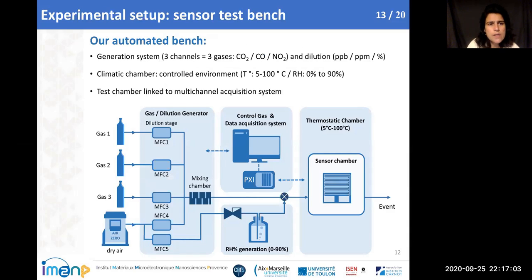Here I present you our experimental setup. We have an automated bench with a generation system, 3 channels, 3 gases: carbon dioxide, carbon monoxide, and nitrogen dioxide, and we can have different dilutions with a dry air gas vector. We have a climatic chamber where we can control our environment, the temperature and the relative humidity. And we have a test chamber with a multi-channel acquisition system, and we have a PXI and a LabVIEW program to control it. And here this is the picture of the generation of humidity.